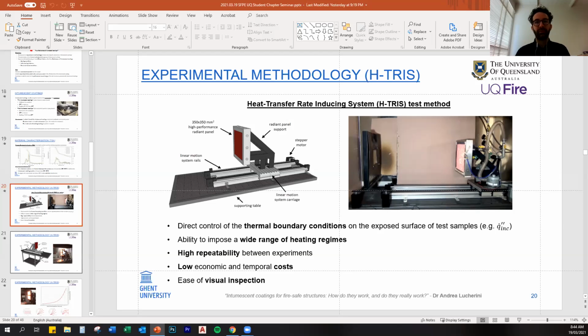But also what I'm trying to make people aware of is that one exposure for this kind of coatings is not enough, because if we design a coating to get a good behavior in the case of a standard fire, it doesn't mean that the coating would behave in a good or effective way in other conditions. Particularly in a performance-based design approach, since it's a reactive material, how can we assure the same performance that we would expect in a very fast growing fire, because the coating needs high temperatures as well? What happens if you have a slow growing fire? You cannot assume the same performance, and I'll give you evidence of that. So this is just the concept and the takeaway message that I would like to give to people.